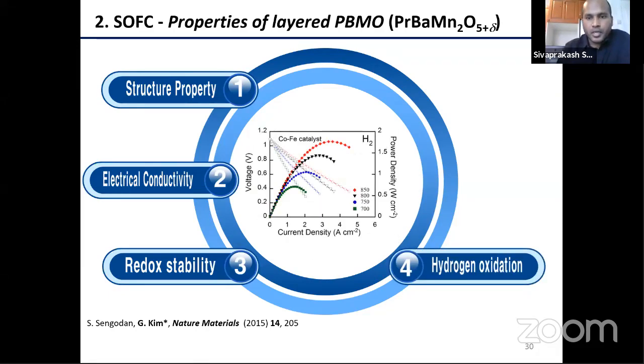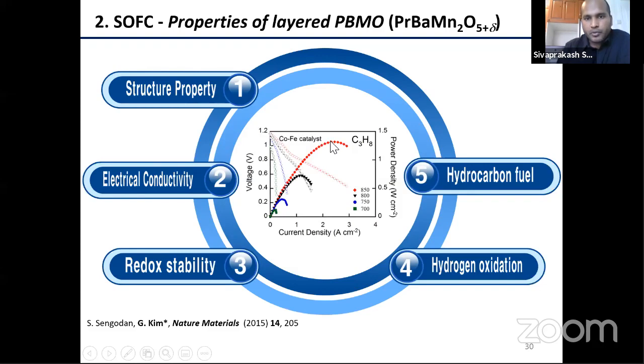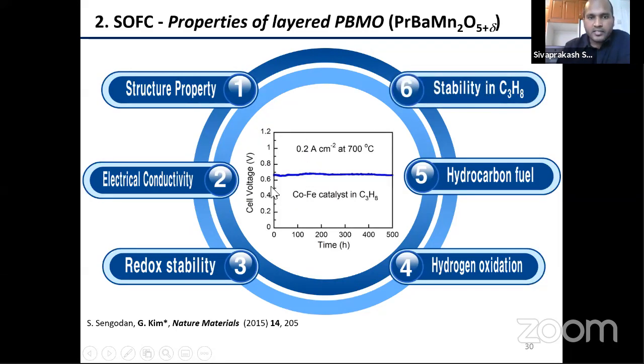It shows very good cell performance in hydrogen-containing fuels. Here it shows the power density in hydrogen: at 800 degrees Celsius, about 1.7 watts. In propane, it shows about 1.2 watts power density at 800 degrees Celsius. The stability is also very good, showing no degradation for more than 500 hours in carbon-containing fuels, whereas with nickel-containing electrode material, degradation is very quick, even within 1 hour.